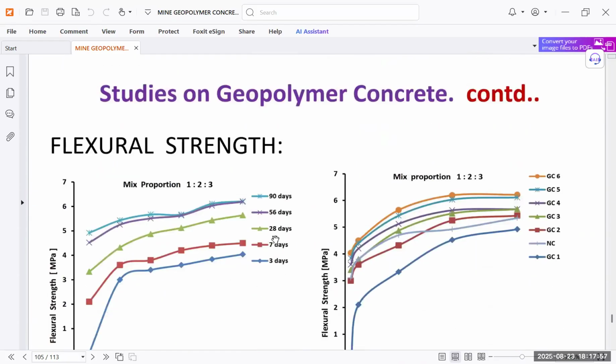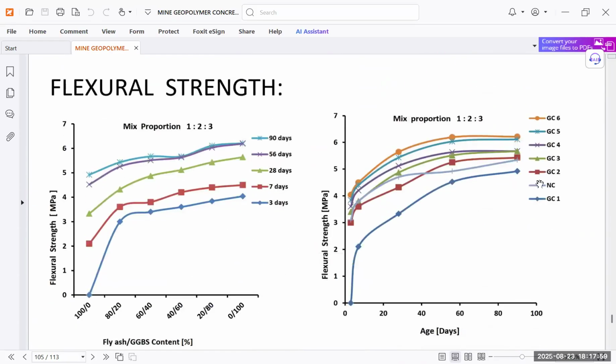Then flexural strength also has been checked. You can see normal concrete flexural strength is something like this, and the geopolymer strength in the GC6 case is something new. For different ages, we can get the required strength by varying the proportions in different geopolymer concretes, so that we can get results more than normal concrete also. So it is more feasible, and we can tailor the properties. It is not fixed that only this much result it will get.